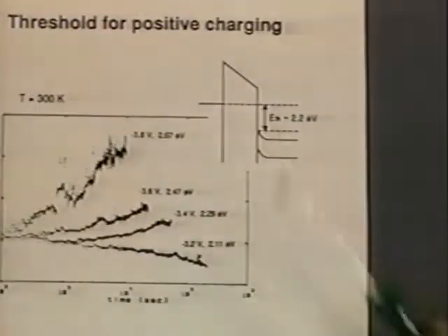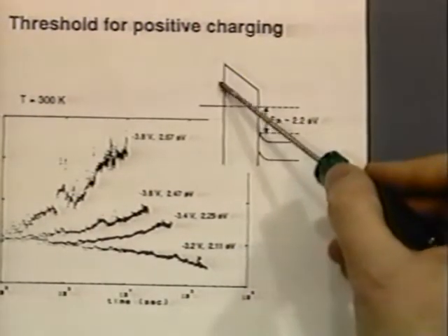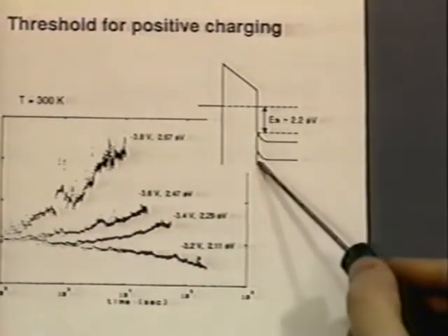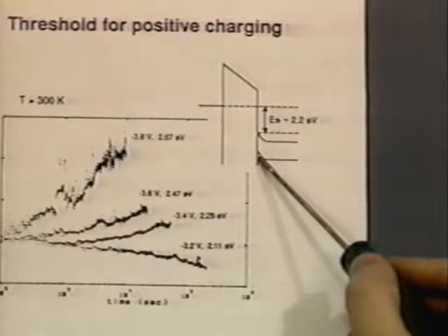Well, it seems to me that if it's voltage, that means energy, right? QV is energy. It may mean energy, but not necessarily. I think it may also mean accumulation of holes. Because, let me find a band diagram for you. For example, using a p-type substrate, as you increase the negative voltage on the device, you raise this level right here, you accumulate holes in this region. Applying the voltage accumulates the holes in this region.